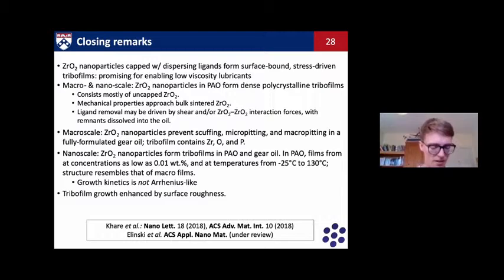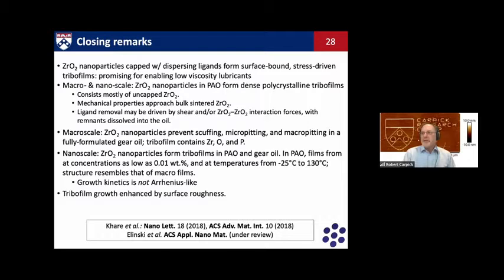So first of all, from Jack Walker, what type of AFM tip was used to achieve the loads for the ZDDP on iron oxide work? Very good question. So initially we used silicon commercial tips that were coated with diamond-like carbon. Those make those tips more wear resistant than pure silicon. Pure silicon is not sufficiently wear resistant. We have since, in fact, been moving towards other tip materials. Even the diamond-like carbon can wear out after long numbers of cycles. So we actually recommend using hard coatings on your tips.